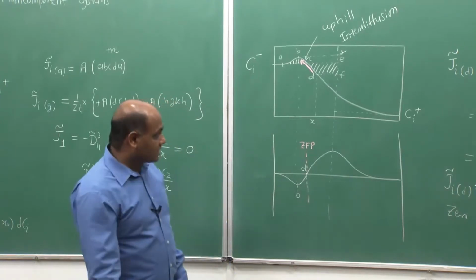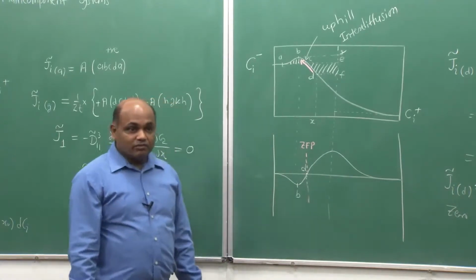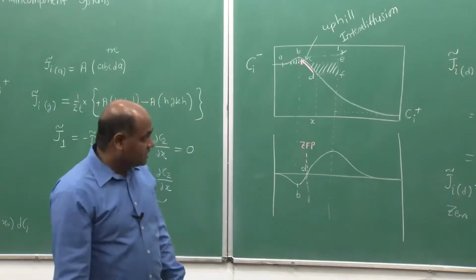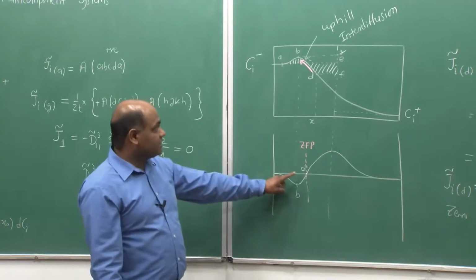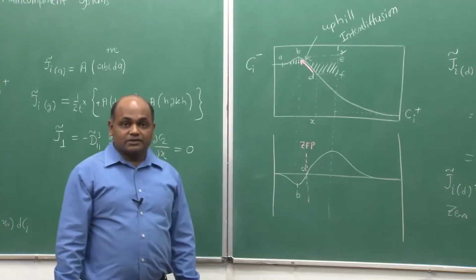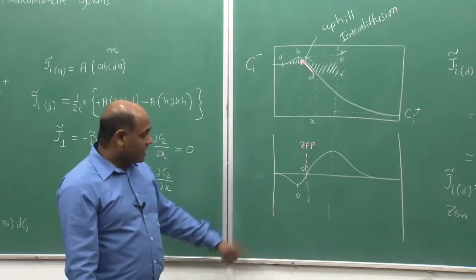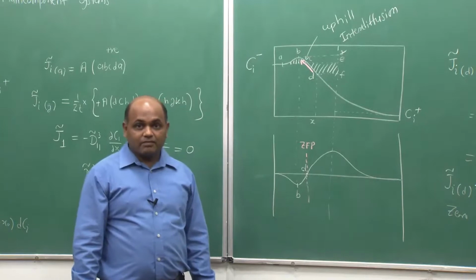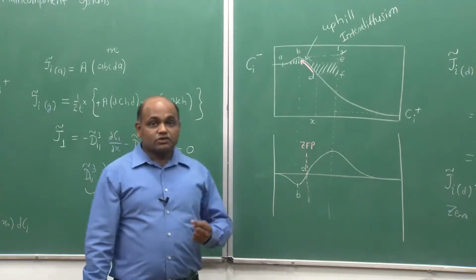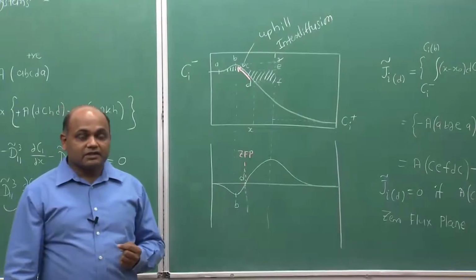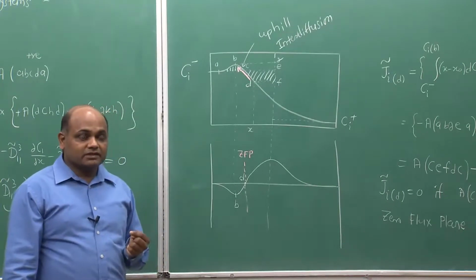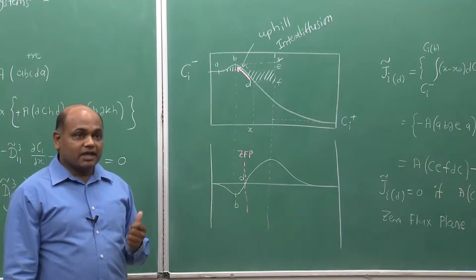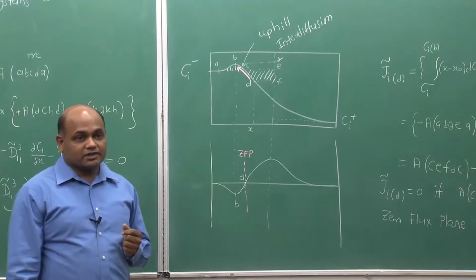These ZFPs are very important when we are studying diffusional interactions, and we want diffusion couples which would develop ZFPs and uphill diffusion regions. Dayananda has studied such couples extensively by forming isoactivity couples. That means, a diffusion couple in which the thermodynamic activity of a component is the same in both the terminal alloys to start with.